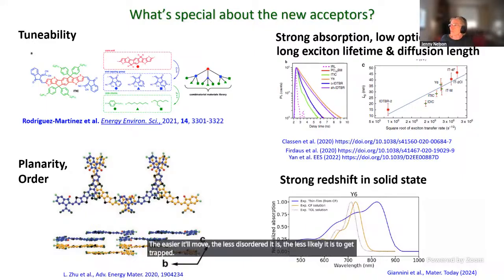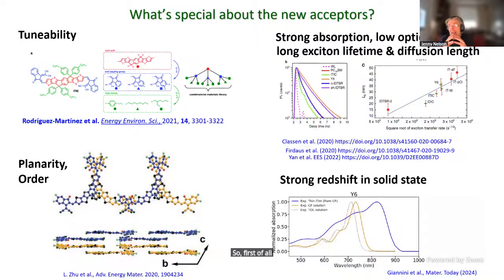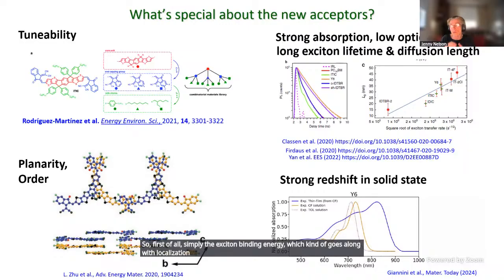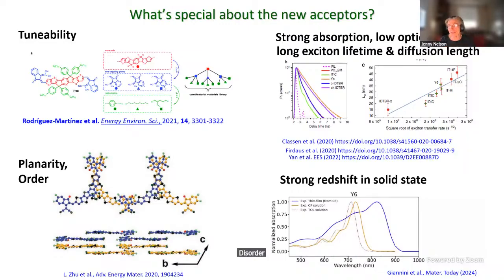So I would say the reasons why the exciton diffusion length was short would be to do with, first of all, simply the exciton binding energy, which goes along with localization, and also disorder in site energies that tends to encourage the excitons to find the lowest energy place and stay there.